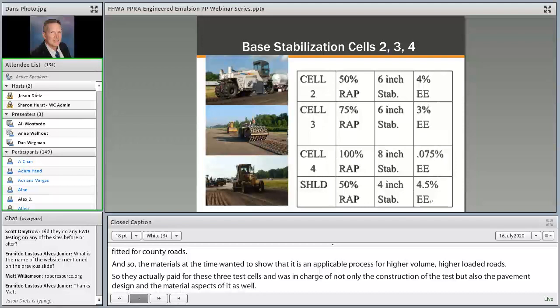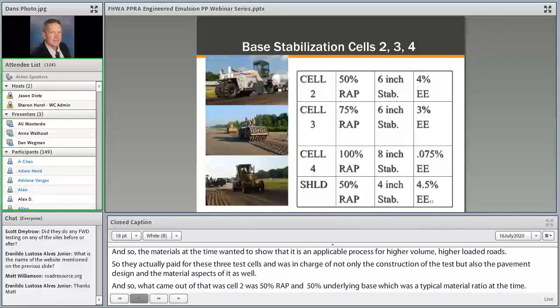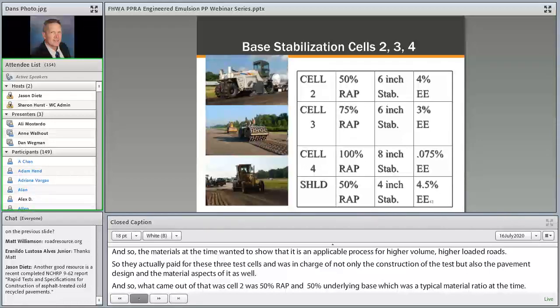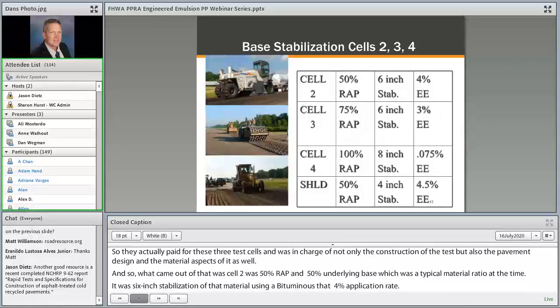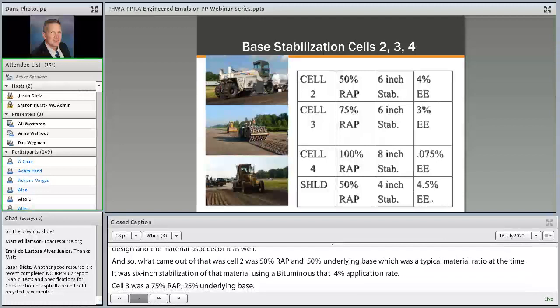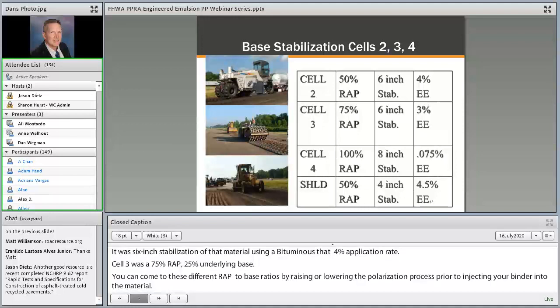It was 6-inch stabilization of that material using an engineered emulsion at a 4% application rate. And then cell 3 was a 75% RAP to 25% underlying base. You can come to these different RAP to base ratios just by either raising or lowering your reclaimer in that pulverization process prior to injecting your binder into the material. It's typically a 2-step process where you go in and grind up the material first and then come back with an injection of the binder into that ground up material.